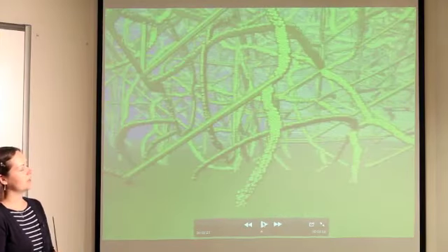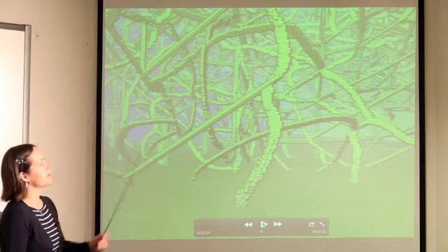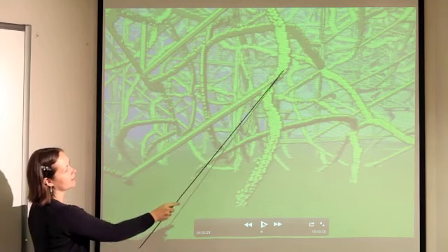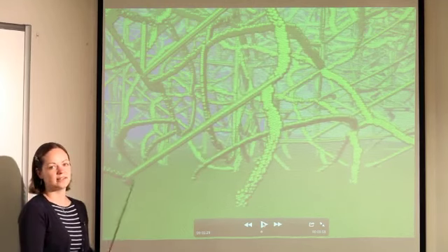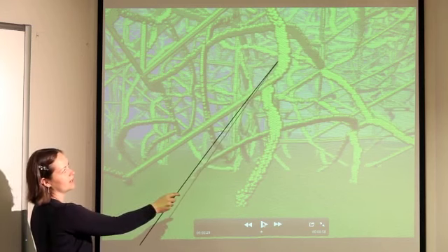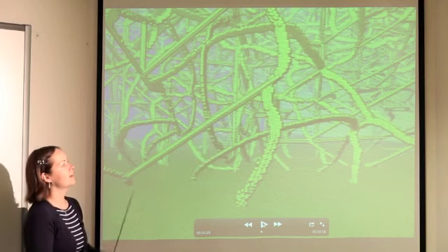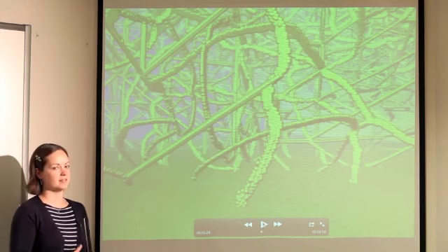And if we pause the video here, then you can see that actually most of the dislocations aren't single rows of atoms. They actually form these ribbons. And the reason for that is that the dislocations dissociate into partials. So there'll be a leading partial on one side and a trailing partial on the other. This bit in the middle is a stacking fault. And then that's relevant for work hardening because it affects things like cross-slip.